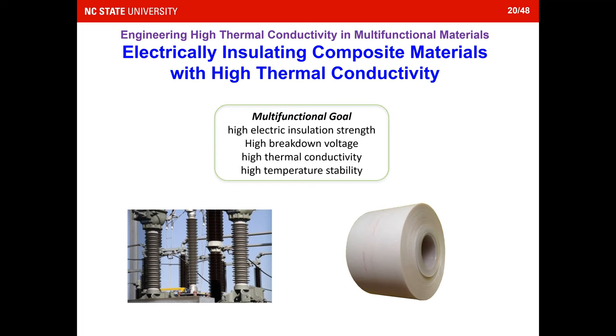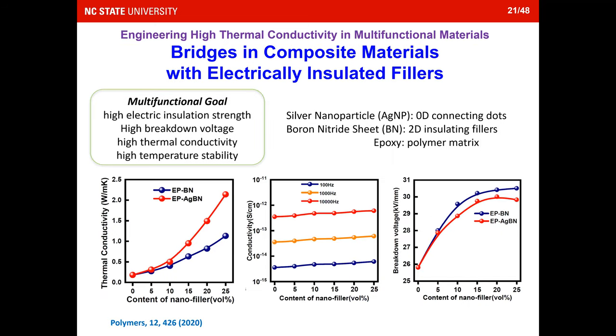stability. So in the second example, this time we're using a boron nitride sheet, which is a two-dimensional insulating filler. But immediately we found that if you just use a two-dimensional insulating filler, it's not enough. So we add some silver nanoparticles serving as zero-dimensional connecting dots. Those particles actually connect those sheets together to form a network. And we're using epoxy as a polymer matrix because it already has pretty good high temperature stability.